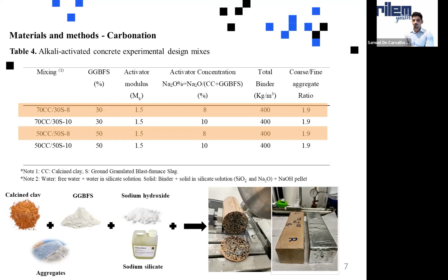We also did the same mix with 70% of calcined clay and 30% of slag, however, you increase the activator concentration to 10. Same thing, you use 50% of calcined clay and 50% of GGBFS with 8 and 10% activator concentration. The calcined clay used in this study was a low-grade calcined clay, as you only have 50% of amorphous phase.